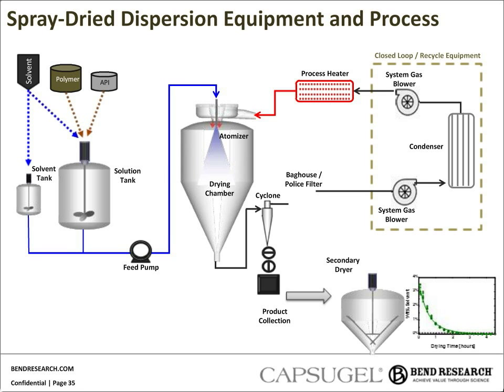The droplets dry to solid particles inside the drying chamber and are pneumatically conveyed to a cyclone separator, where the majority, usually greater than 90% of the SDD product, is removed from the gas stream using the centrifugal forces generated inside the cyclone. The remaining solvent-laden drying gas is passed through a police filter to remove fines, and then in larger scale spray dryers it's recycled through a condenser to remove the solvent vapor, and then back into the drying gas heater and into the drying chamber. Smaller scale equipment is often operated in single pass or open loop mode, and in those cases a fresh nitrogen gas stream passes only once through the dryer and is vented to a waste stack.